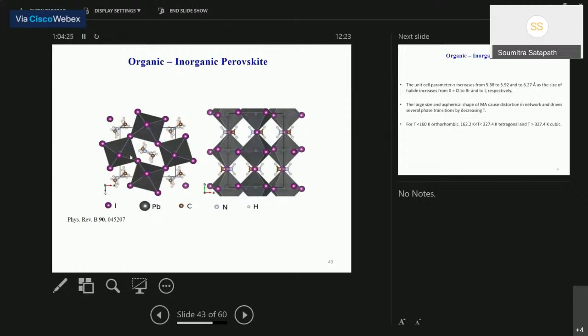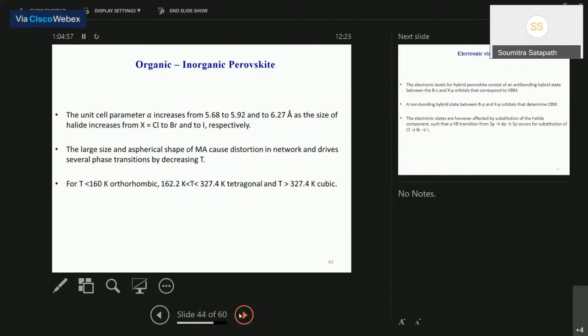The interesting thing is that if you change these halides, for example, if you replace chlorine with bromine with iodine, your unit cell parameter is changing, and that changes the whole structure and induces distortion in the structure. Similarly, in this void we have put MA right now. Instead of that, if we put some larger or smaller organic cation, that also can induce some kind of rotational distortion in the structure, and that changes the band gap of the material. For example, if I change from chlorine to bromine to iodine, the unit cell parameter changes from 5.68 to 5.92 to 6.27 angstrom, and changes the band diagram.